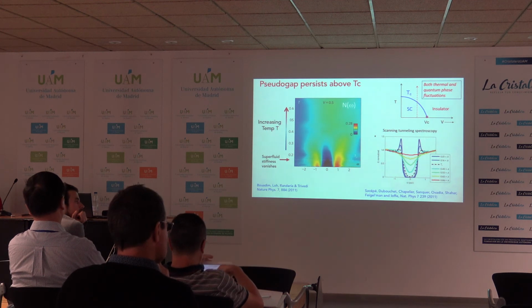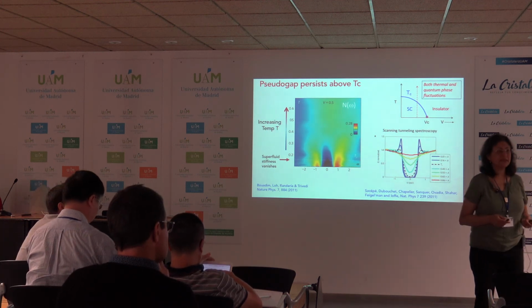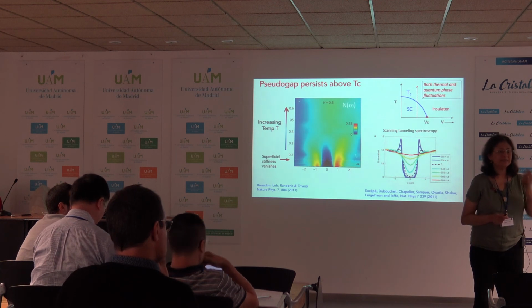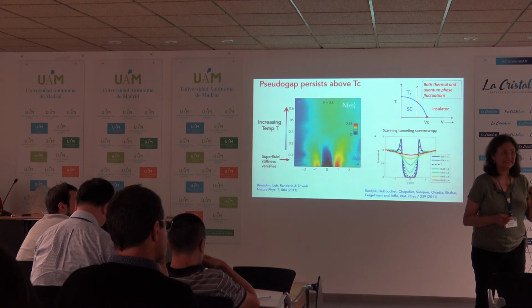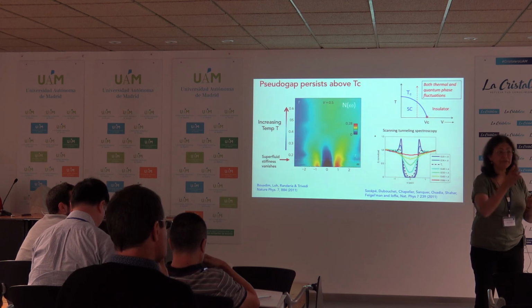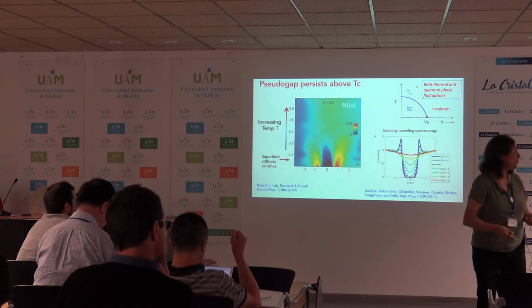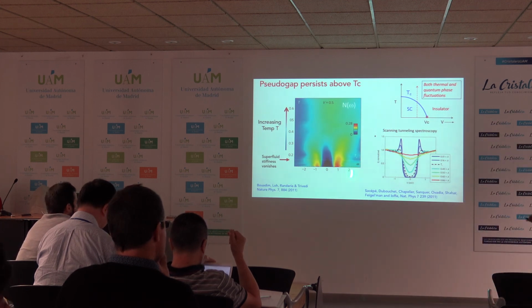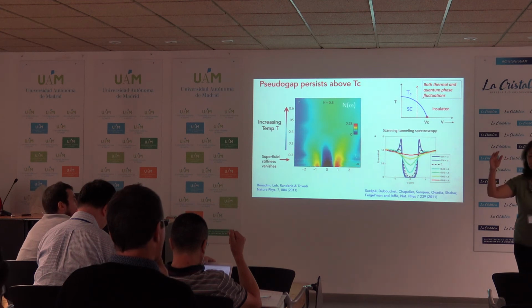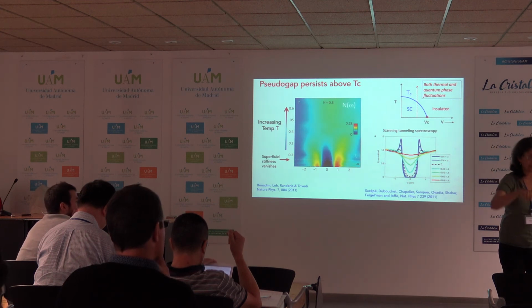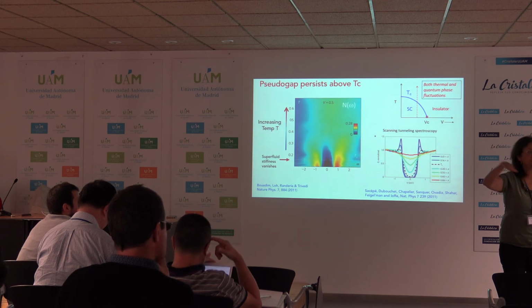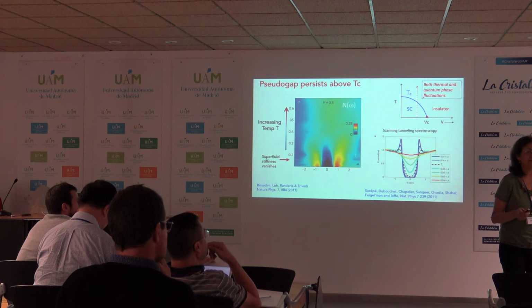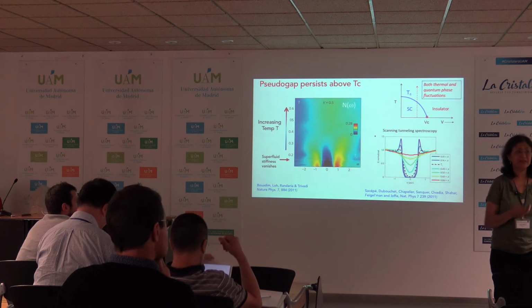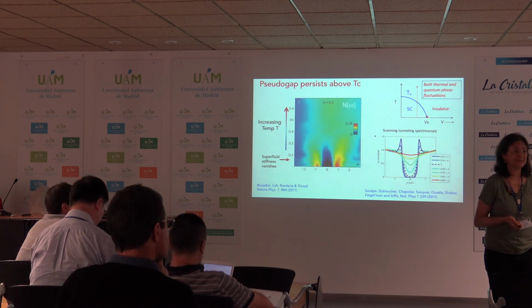Yeah, so we have done quantum Monte Carlo on that. I don't have that result here. So again, resistivity is the first measurement experimentalists do, but theoretically it's hard to calculate. But we do calculate that current correlator that I mentioned, and a different limit of that gives you resistance. So we are able to get the resistance versus temperature and get Tc, and then you can see the whole sequence of curves, just like the experimental curves. And the transition, in fact, I should include that, it's rather beautifully at the quantum of resistance. So we obtain it from the current correlator.